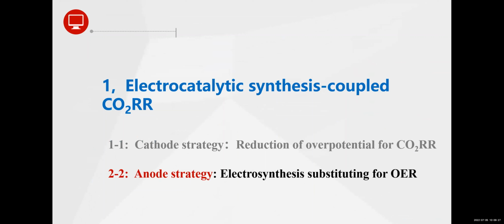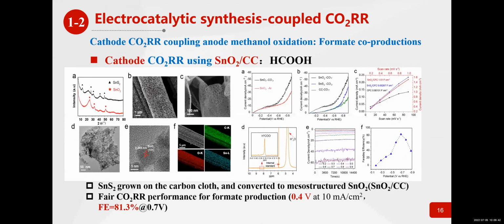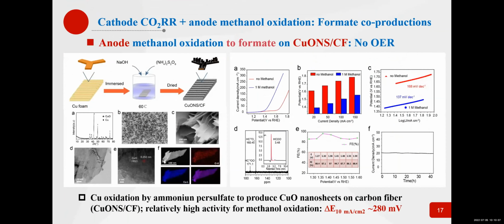Next, we will move to the anode strategy: how to realize the synthesis of chemicals at the anode to substitute for the common OER process in coupling with the carbon dioxide reactions. Here we use tin oxide catalyst loaded on carbon cloth, and this catalyst catalyzes the carbon dioxide reactions to produce formic acid. This shows relatively good activities for these reactions. And then at the anode, we use copper oxide nanosheet loaded on carbon fibers, and this material is used to oxidize methanol to formate.